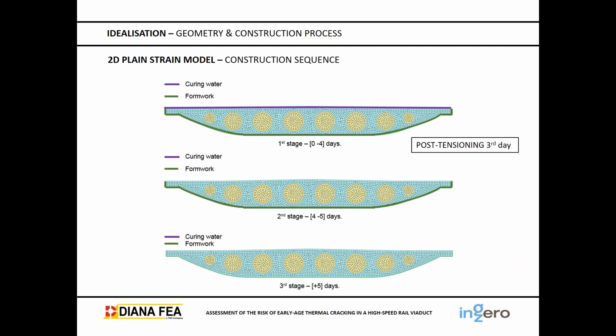from the start to 4 days. They do the post-tension between the third or the fourth day, okay? In this stage, we are curing. What was done on site was the formwork was placed and there was curing water. The deck has been ponding with a permanent layer of between three and five centimeters of water on the top side.